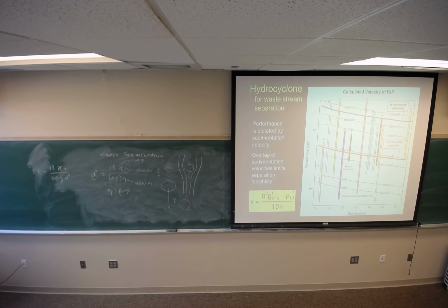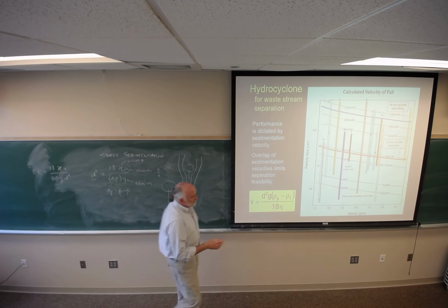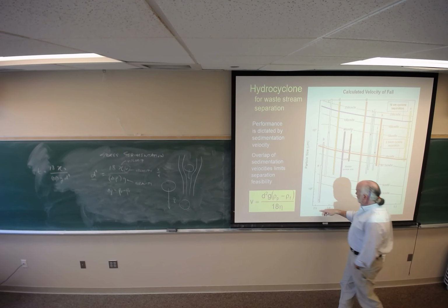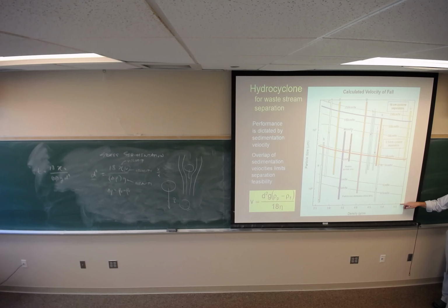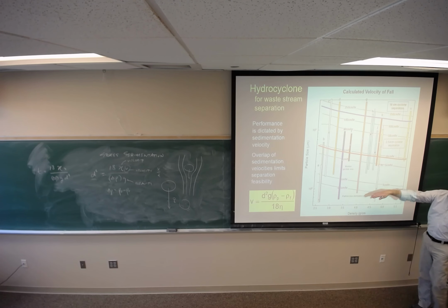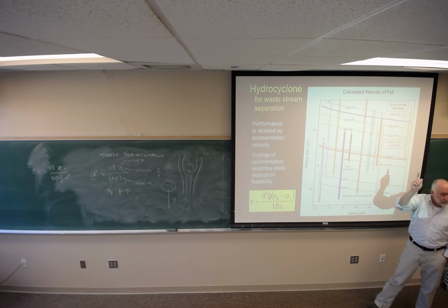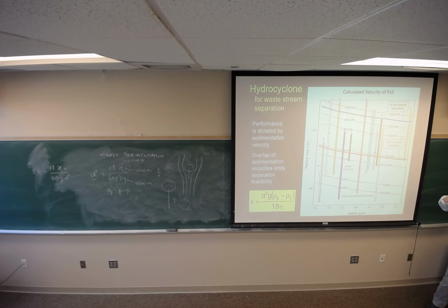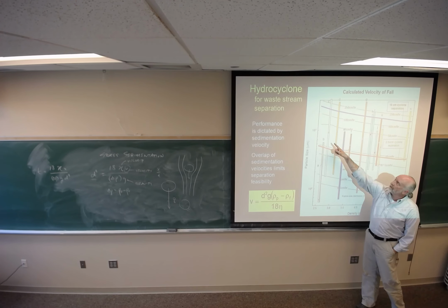So this whole thing about glazed waste and waste in an industrial process, we could potentially use it for beneficiating other waste streams, provided that my particle size and my densities are not offsetting, if you will. And that's what this plot is showing us. The x-axis is density. We go from about 2.6 up to a little over 5.5. And then I have particle size on the y-axis on a log scale. That's really important for us that it's on a log scale. So here's 1 micron, there's 10 microns, etc.